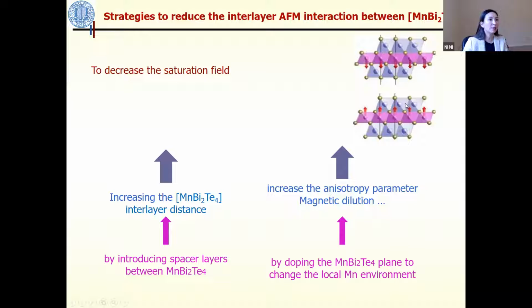So how can we increase the 124 interlayer distance? One way we can do it is by introducing spacer layers between them. So that's strategy 1. And strategy 2 is we can dope the 124 plane to change the local manganese environment. By this way, we may be able to increase the anisotropy parameter, or we may introduce some magnetic dilution effect. We don't exactly know. However, there will be a chance that by doping the 124 layer, we will be able to change the manganese local environment.